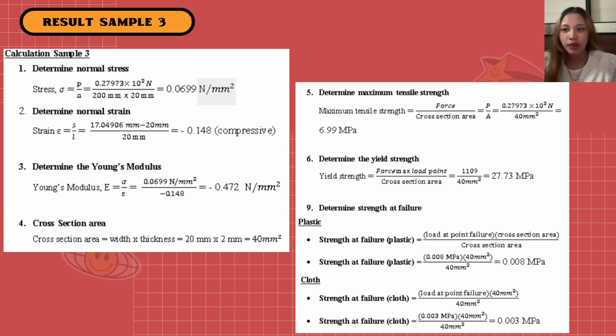Young modulus for sample 3 is -0.472 Newton per millimeter square. The cross section area is same as sample number 1 and sample number 2, which is 40 millimeter square. Maximum tensile strength, we got 6.99 MPa. Yield strength 27.73 MPa, and then strength at failure same like sample number 1 and sample number 2, which is 0.008 MPa for plastic, and then 0.003 MPa for cloth.